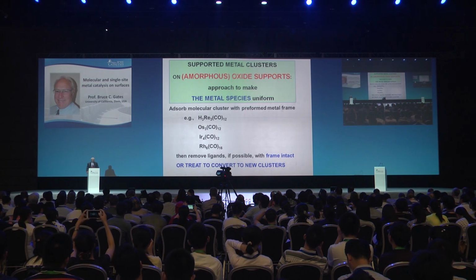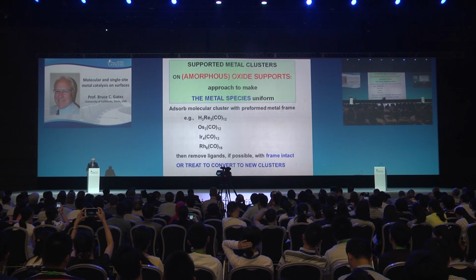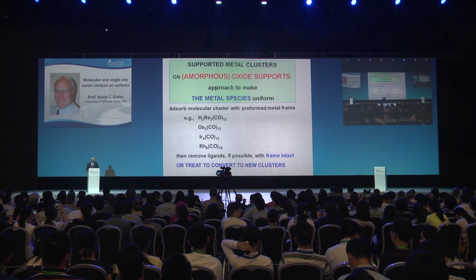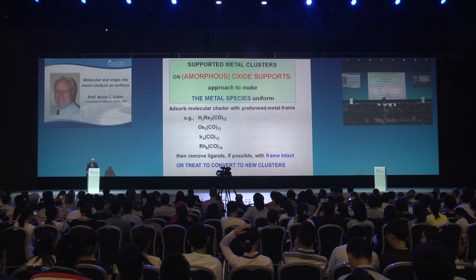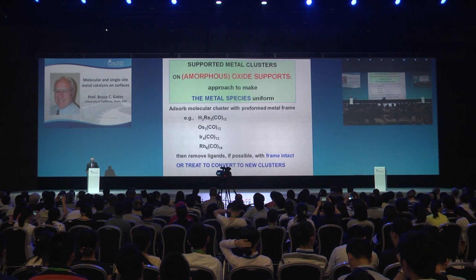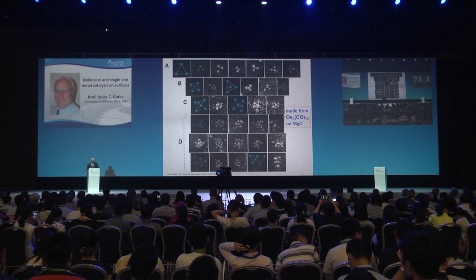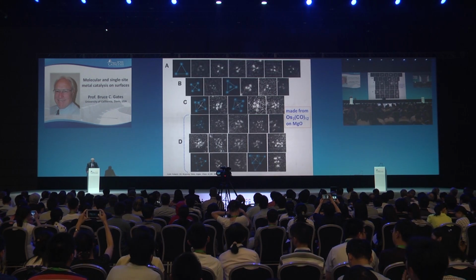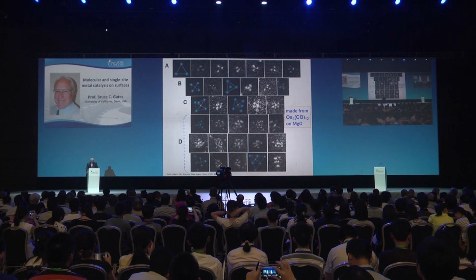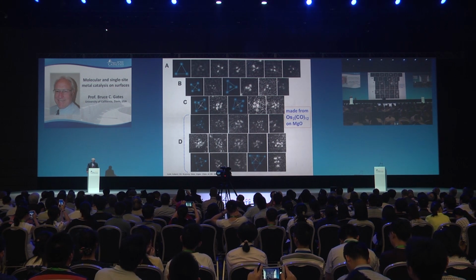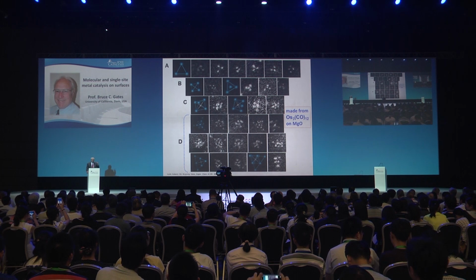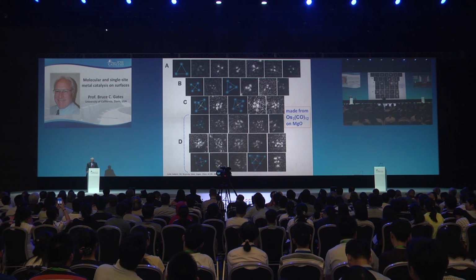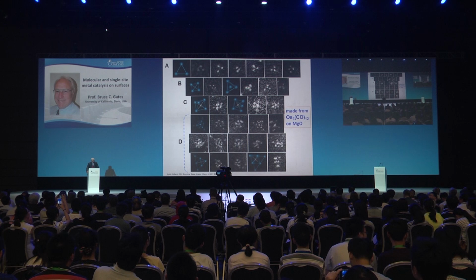Just want to mention that one can put a number of metal clusters onto supports, including amorphous supports, so all the common catalyst supports. These are examples. One can use osmium, triosmium dodecacarbonyl as a precursor, put it on MgO, treat it under conditions that in solution give a family of osmium carbonyls, and find the same family on the support.